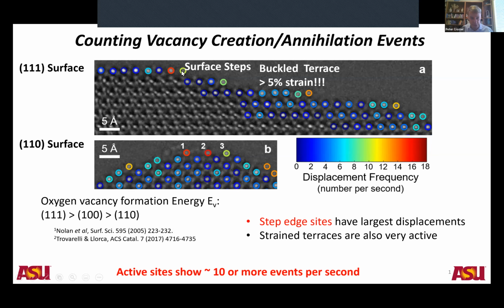And what they've done here is they've simply counted the displacements of the cation in each frame of the movie. And so what you're looking at now, the coloration that you see now is the displacement frequency, how many times the cation moves per second, which is indicative of the creation and annihilation of oxygen vacancies. And again, you see a similar kind of behavior here. The 1,1,0 surface is much more active than the 1,1,1 surface, and the defects on the surfaces are much more active than the perfectly unstrained terraces.